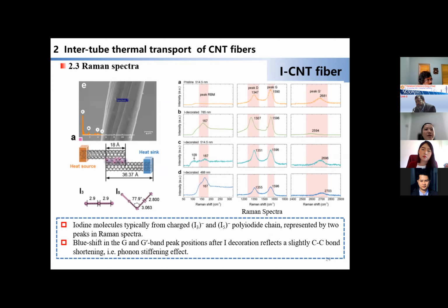The following is the Raman spectra for different CNT fibers. We use Raman spectra to investigate the change of phonon vibrational modes of CNT fibers after decoration. Iodine molecules typically form charged I3, I5 chains, represented by two peaks in the Raman spectrum. The blue shift to the right in peak positions after decoration reflects a slight carbon-carbon bond shortening, that is a phonon-stiffening effect.